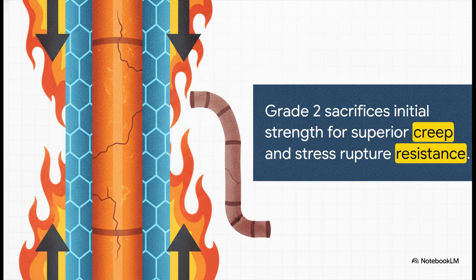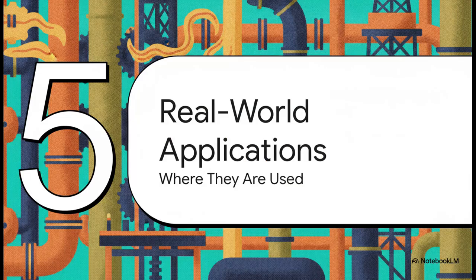Grade 2 sacrifices that initial tensile and yield strength to gain something much more important for its specific environment: superior long-term creep and stress rupture resistance. You see, when a pipe is operating at 1500 or 1800 degrees Fahrenheit under immense pressure, the primary failure mode isn't just bursting instantly, it's creeping. It's slowly deforming over time and eventually rupturing. The higher temperature solution anneal of grade 2 gives it the absolute perfect metallurgical structure to resist that high temperature creeping.